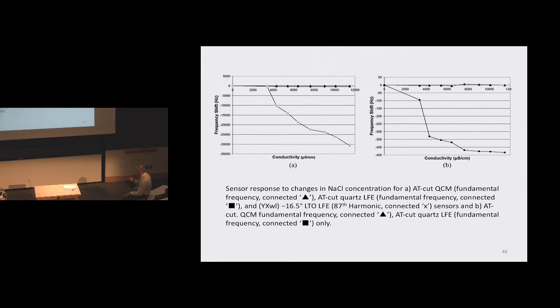How does it work? It worked reasonably well. Here's the response to sodium chloride, AT cut, fundamental quartz. That's given on the top as the AT cut. LFE and the QCM, they seem to be virtually one on top of the other. This is the lithium tantalate one. Look at these changes. These shifts are huge, all right?